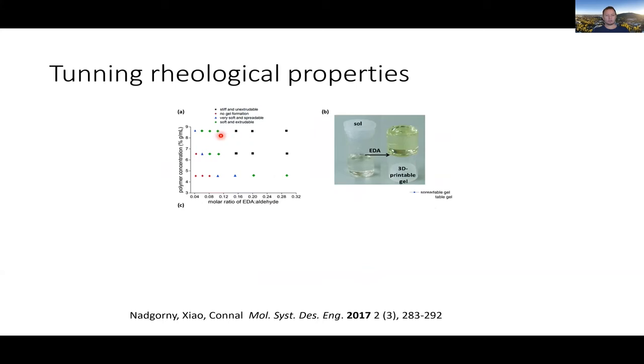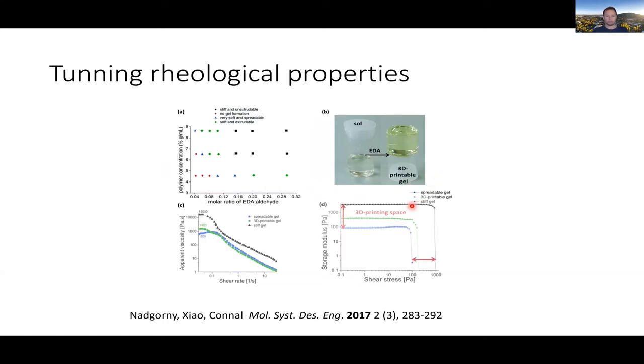So this gets to this tuning of rheology. We're tuning the cross-linker ratio, we're tuning the composition, and these green dots here are where we can form a soft and extrudable gel, which is sort of our criteria for 3D printing. And so we can do some more rheological analysis on this. Depending on the storage modulus, we're relating this to how that fits into this 3D printing space. And yeah, this is the apparent viscosity here as well.